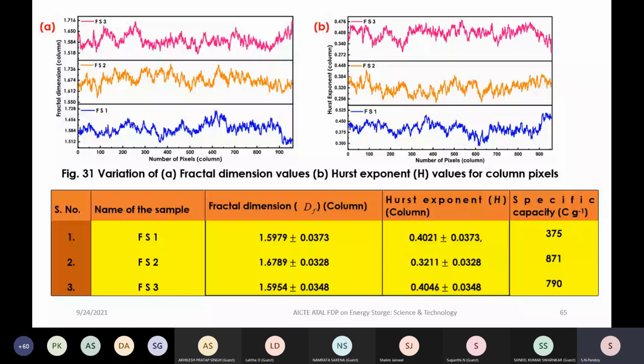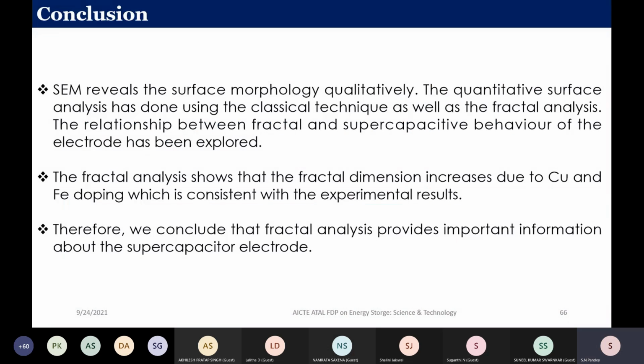1.6789, and one can see that the highest fractal dimension corresponds to the highest value of the specific capacity. So this is also supporting this experimental result. So one can conclude here that SEM reveals the surface morphology qualitatively, and the quantitative surface analysis has been done using the classical technique as well as the fractal analysis. The relationship between the fractal and supercapacitive behavior of the electrode has been explored.